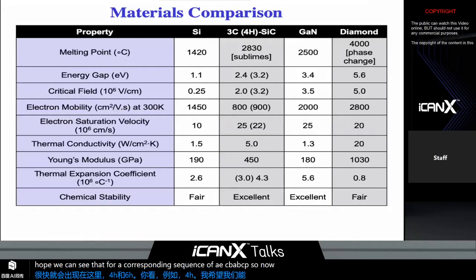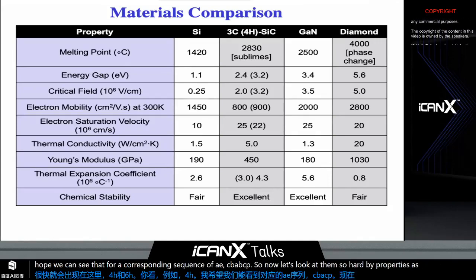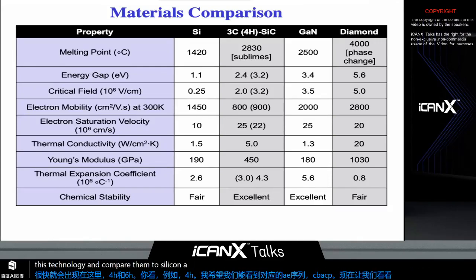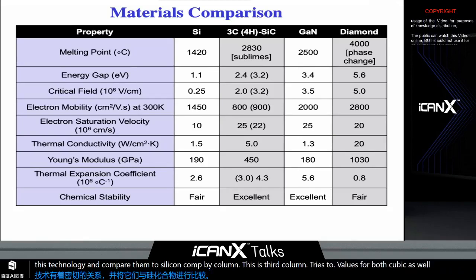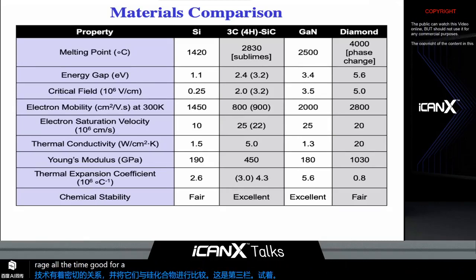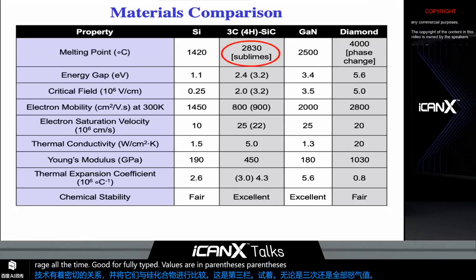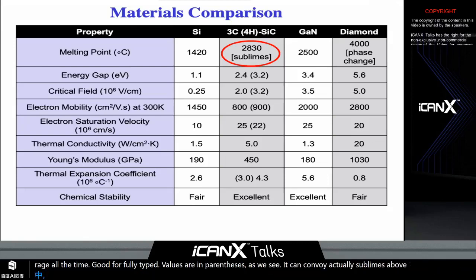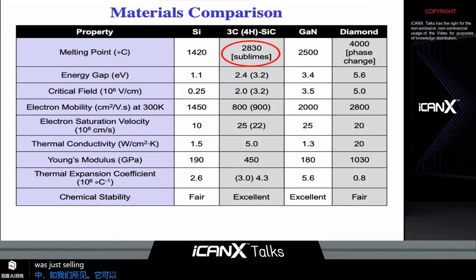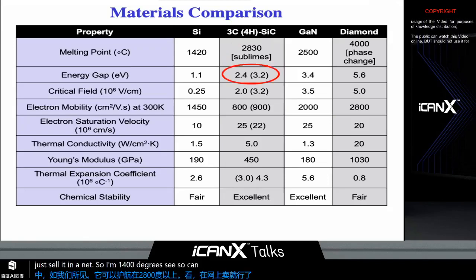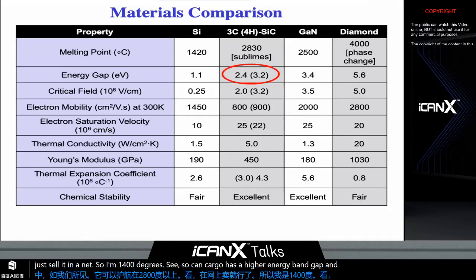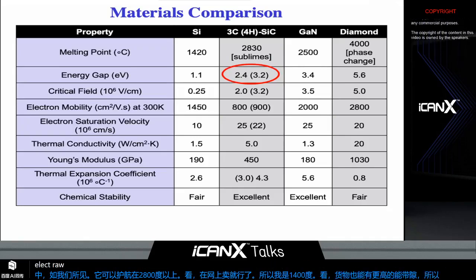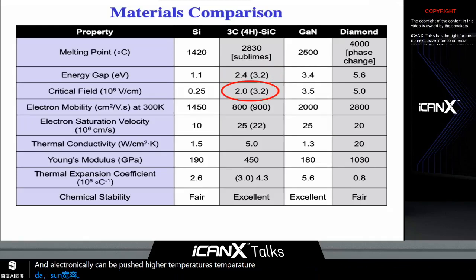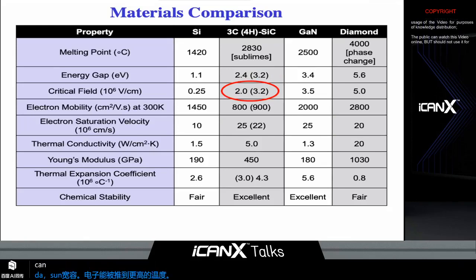So now let's look at silicon carbide properties of relevance to this technology and compare them to silicon. The silicon carbide column, the third column, has the values for both cubic as well as the 4H polytype. The 4H polytype values are in parentheses. As we see, silicon carbide actually sublimes above 2800 degrees C, as opposed to silicon that melts around 1400 degrees C. Silicon carbide has a higher energy band gap, and so it is more radiation tolerant and electronically can be pushed to higher temperatures. Silicon carbide has a higher critical or breakdown field compared to silicon, which allows silicon carbide devices to operate at higher voltages.